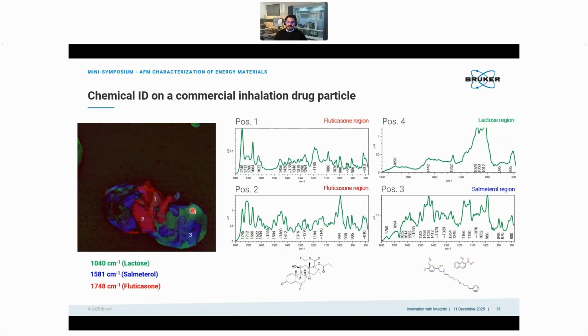So the green area is the lactose, the blue area is the salmeterol. So you can identify, image-wise, the different components of the drug. And obviously you can go and take different positions and extract the local spectra there. So this is very interesting for industries or research on drug delivery, because, as you will see further in the slides, we also have the possibility to image not only on the surface, but even go below the surface. So be sensitive to information from below the surface. And that's where you can think about chemistries in a shell, where basically we will be able to look at them.